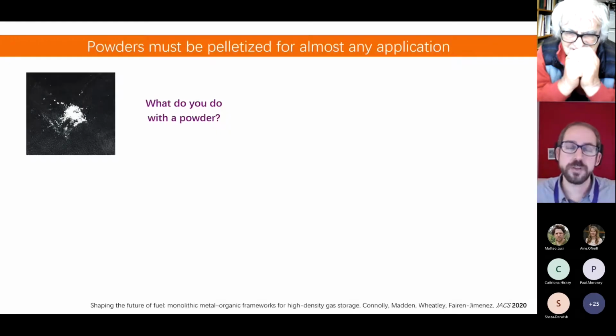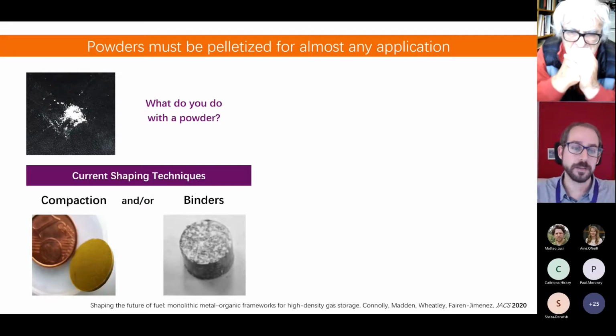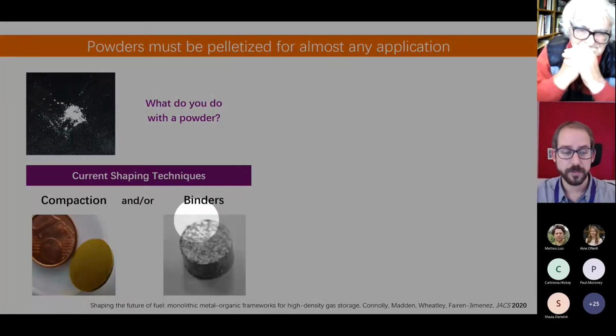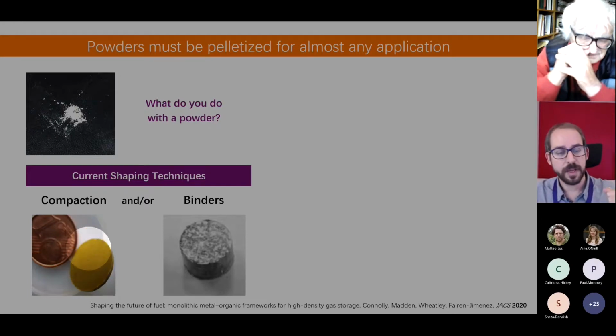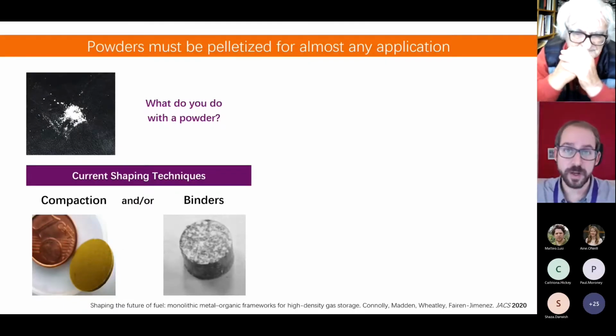A powder will have a huge pressure drop in a system, so at the end of the day, you need to shape this into some pellets, and there are different ways of doing this. You can use high pressure, you can use a binder. And what is the problem? You remember I was telling about MOFs and saying that mechanical properties was a big thing. They don't have really good mechanical robustness. So if we try to pelletize this and we apply very high pressure, we collapse the porosity of the material. We have thousands of square meters per gram, but as soon as we try to pelletize these structures, we destroy all this porosity.